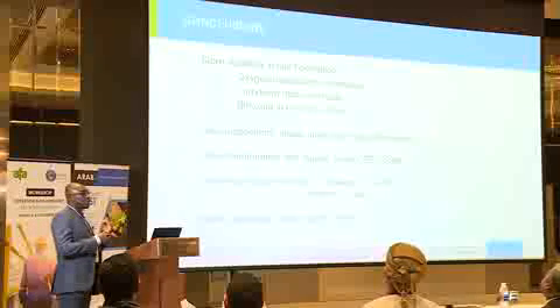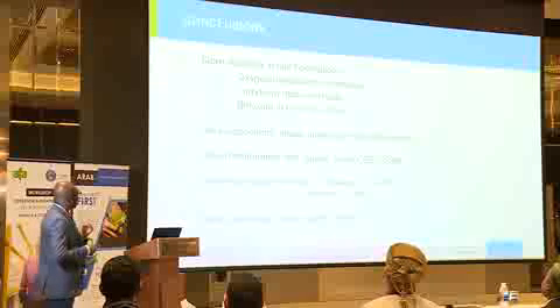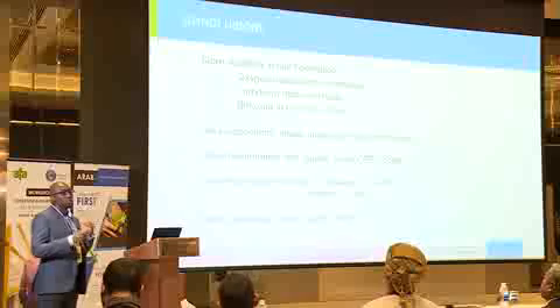When they opened the stripper later on to check, because the stripper is the most critical equipment in this case, it was fine. So we also have a plant that runs at 0.1 volume % oxygen, and also there are no issues. So you have an advantage on your turn down ratio. And another thing is that when you operate a plant with Safurex, the requirement to block in for only 72 hours is removed. So now you don't have a blocking in time period restriction.